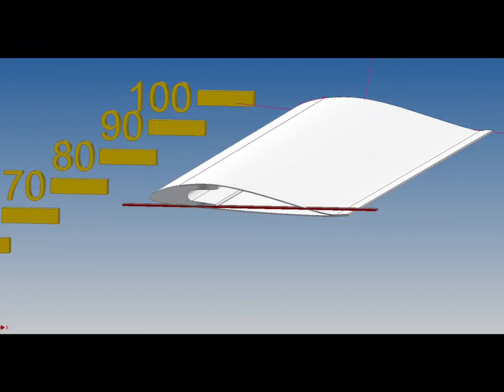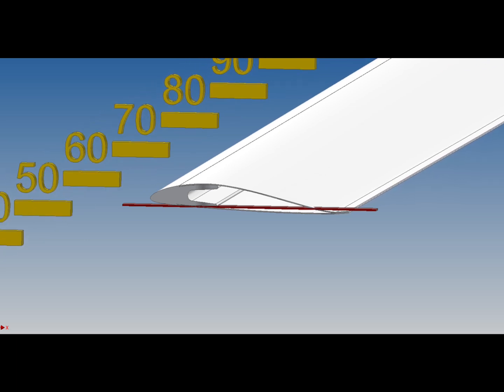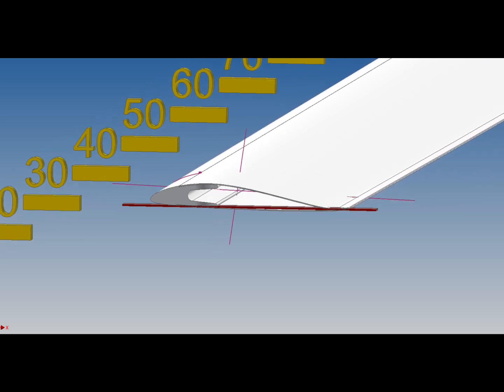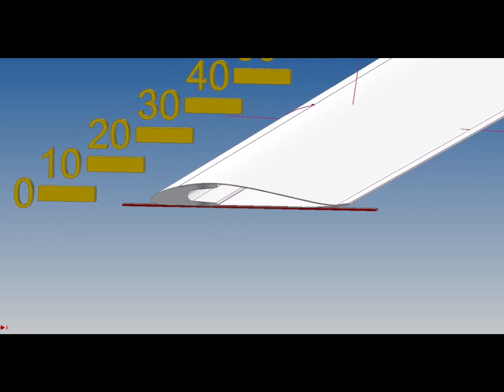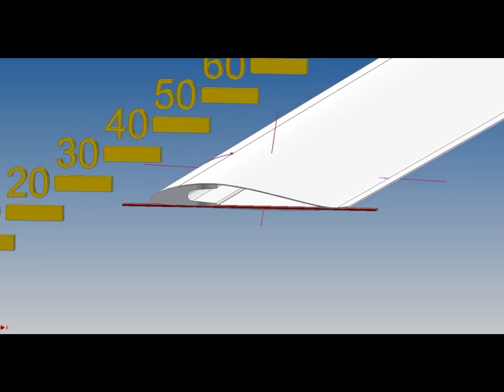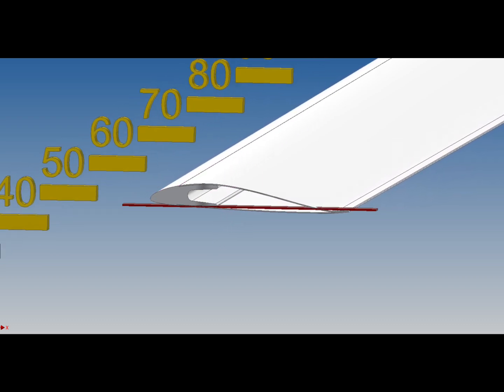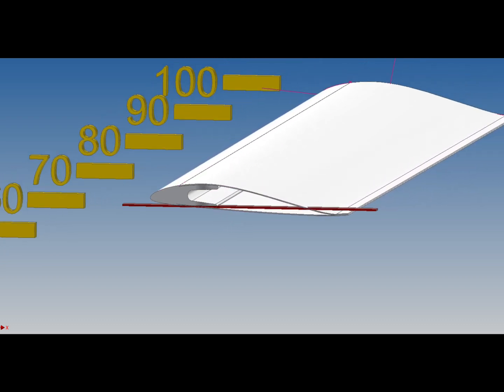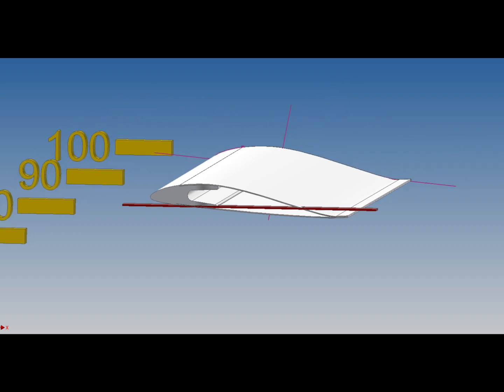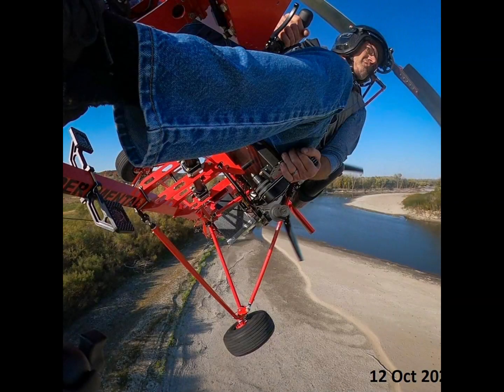Rotor blades feature a non-linear positive twist of 5 degrees. Non-linear meaning the increase of the angle of attack does not progress evenly from the root to the tip of the blade. The first 2 degrees of twist happens in the first 30% of the blade, with the final 3 degrees slowly diminishing as we progress out to the tip. This has required a lot of design and manufacturing efforts, but it results in some wonderful performance.